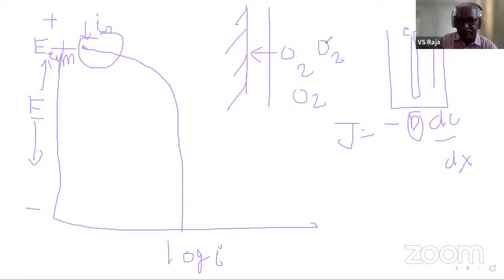Initially, the concentration of oxygen in the bulk and at the surface are the same. When the reaction occurs, the oxygen concentration decreases. And when you increase the voltage more and more, faster reaction occurs. Please see, the rate of reaction increases like this. The oxygen starts moving here. Now, at one stage, the oxygen concentration on the surface becomes zero. What does it mean? The moment oxygen reaches the surface, it immediately gets reduced. The surface concentration of oxygen is zero here.